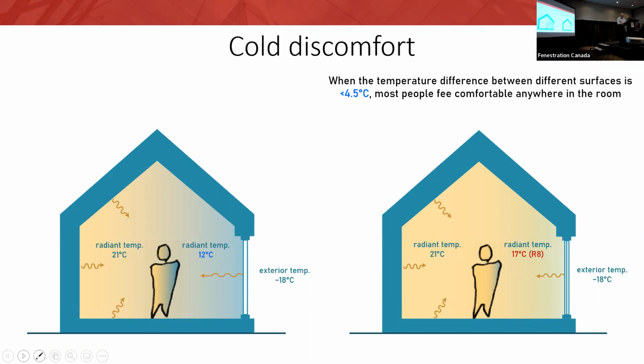So if we have a situation where the indoor radiant temperature is 21, even if it's -18 outside, that's the NFRC winter design conditions. If you have glass that will give you up to around 17 degrees Celsius, or R8 in an R8 window, you've got that comfort condition where you don't have to feel cold discomfort, even with a large glazed surface.